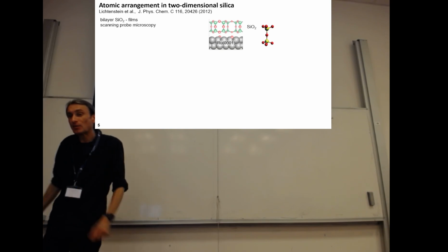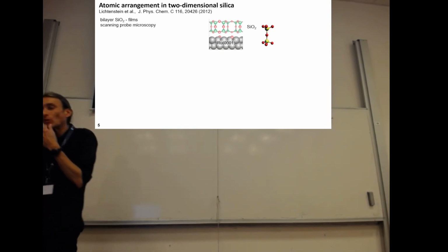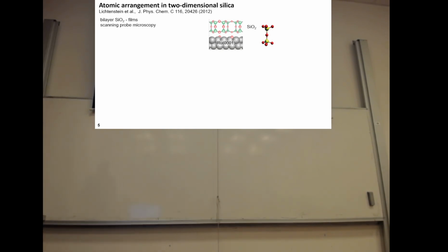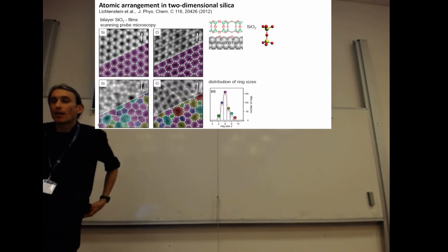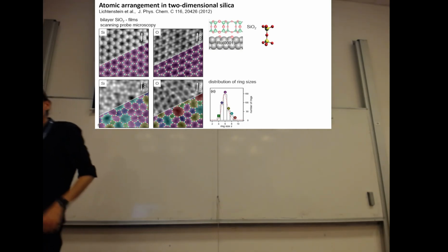Recently people actually managed to look inside these amorphous materials using scanning tunneling microscopy. For this, however, it's necessary to make a rather flat amorphous material. This is actually just a 3-atom thick layer of silicon oxide floating on a ruthenium surface, and this allows you to do microscopy images. This is one of these results.